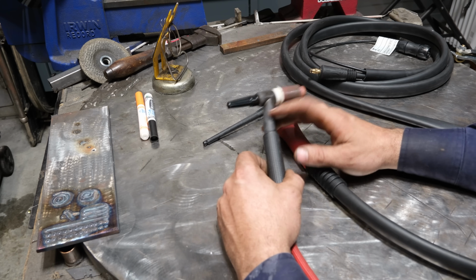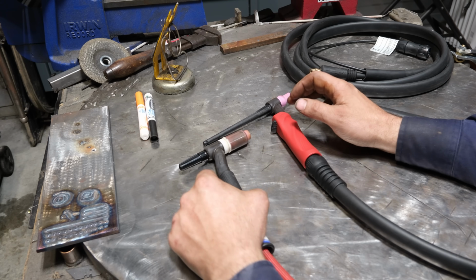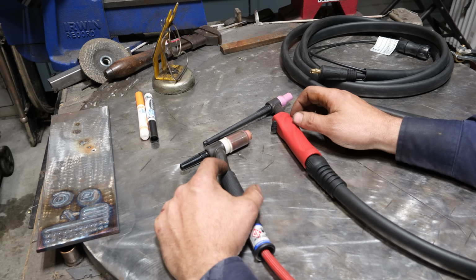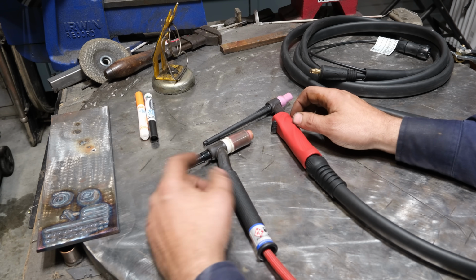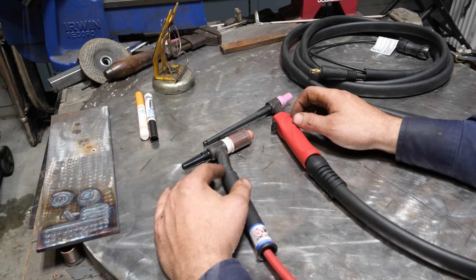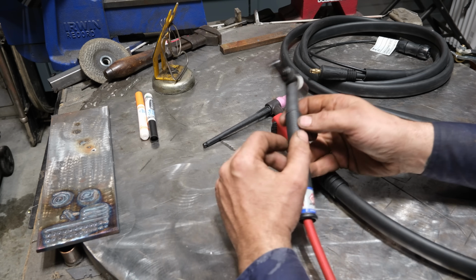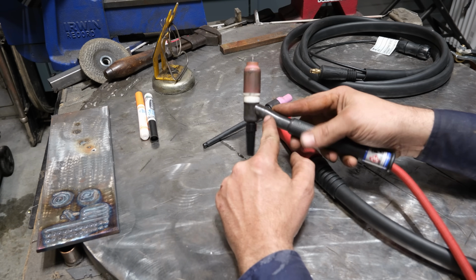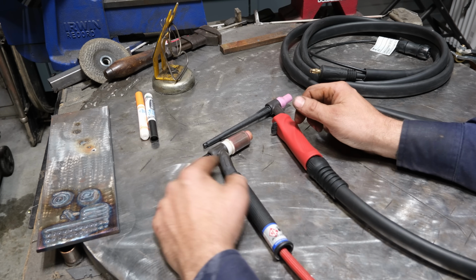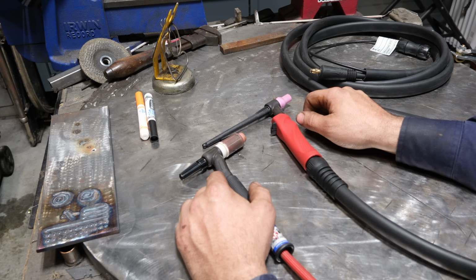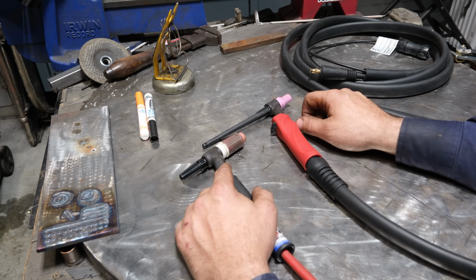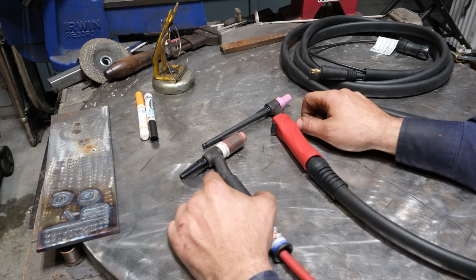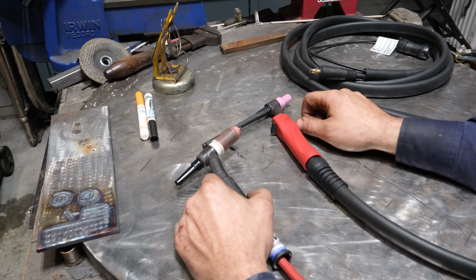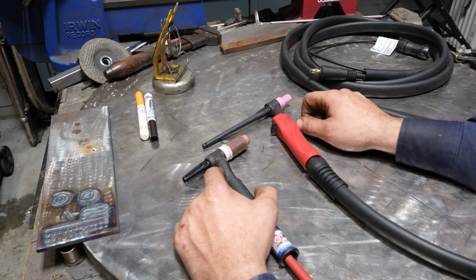Now, this is a 150 amp CK 17 style torch, probably the most popular torch style out there. And it will handle 150, 160 amps on DC without too much issue. But when you start talking AC, this simply doesn't hold up. And I don't know if you can tell by how gray this is. This thing has been almost on fire when I'm welding at 200 amps on AC. So don't do like I do and abuse it. You're not going to get the longevity out of these, and these are a couple $100, so it's not smart.